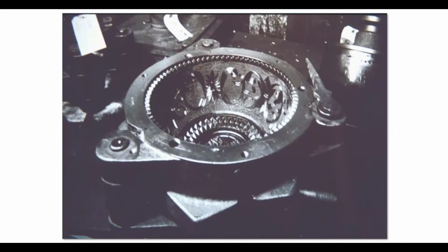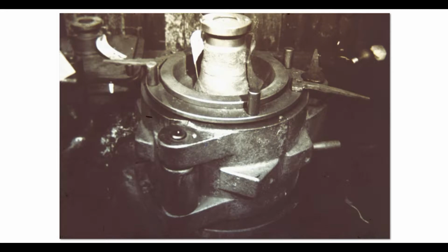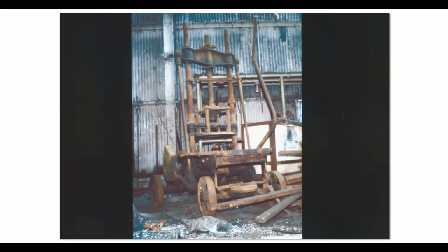This is the inside of one of those molds that I was showing you, made out of iron, and then they would have a lot of machine work inside to do the fancy work that would make the design on the glass. That's the mold with the top and the plunger on, and that was put in a press where the plunger was pushed down to make sure that the glass went to the whole inside, covered. It filled up all the little nooks and crannies of the mold. This was a press. This was in the factory down there. I photographed that. That's what they used to push the plunger down in the press that would complete the process of making a piece of molded pressed glass.